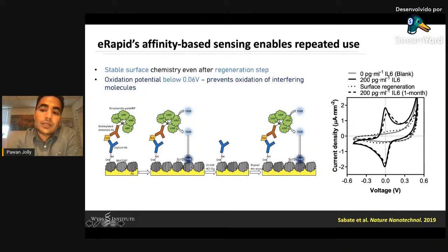The other exciting thing I would like to point out over here is our oxidation potential. So our oxidation potential is close to zero. Now that is really exciting for electrochemistry, because any potential which is above a certain range can actually cause interfering signal. And this interfering signal can come from uric acid, dopamine, tryptophan, because you can actually directly oxidize these onto the gold electrodes. So since our oxidation potential is close to zero, we actually avoid all those kind of interfering molecules, leading to very minimal background in our electrochemical signals.